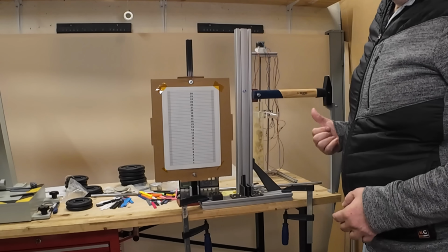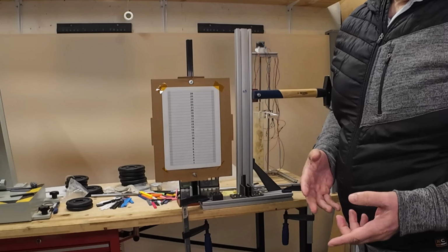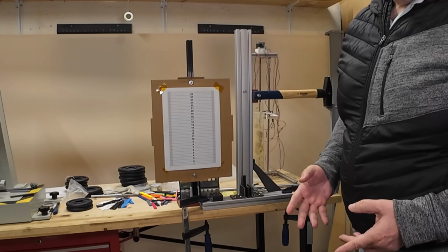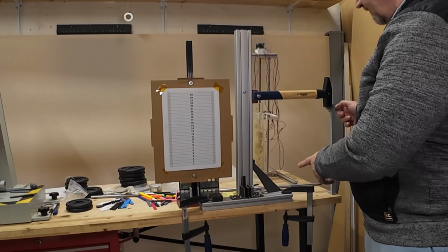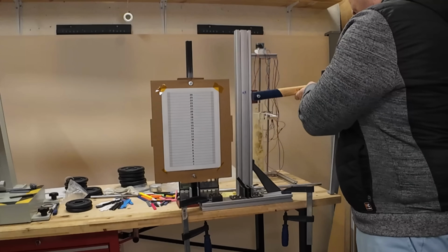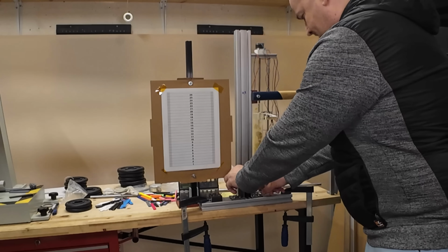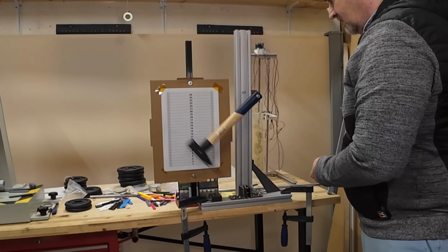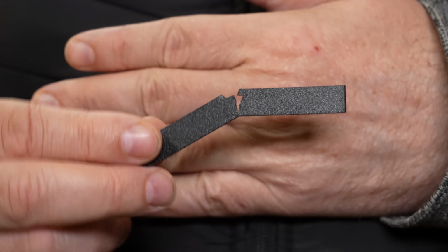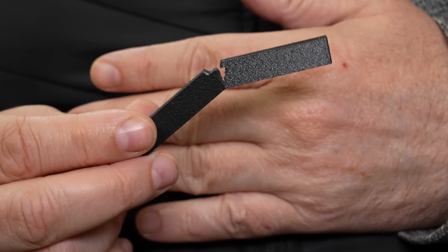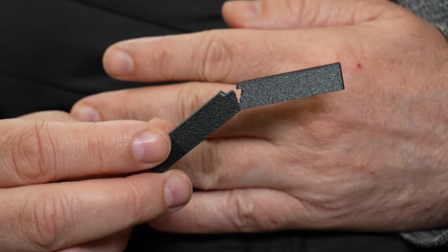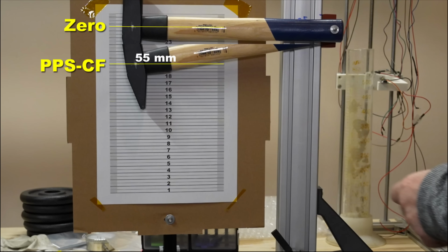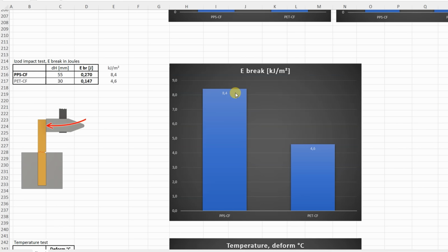Impact test with this half kilogram hammer, and sometimes weaker layer adhesion will result in better impact resistance. Let's see it. Zero position. It's not completely broken, which is not too often the case with these carbon fiber reinforced materials, but let's analyze the footage. These are the edge positions of the hammer, and from the difference in height I can calculate the breaking energy. It is noticeably tougher compared to the PPS-CF.